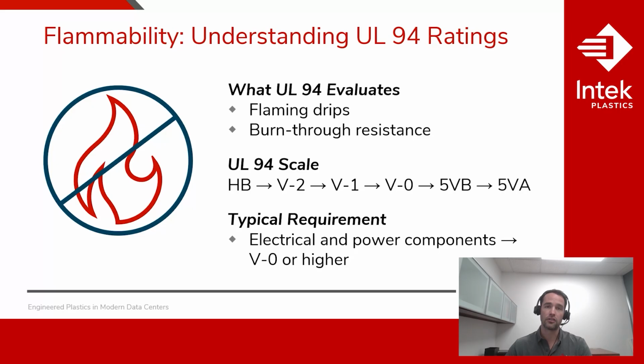For the most demanding applications, you'd be looking at the 5V tests, of which there are 2 ratings. And this utilizes a specimen oriented horizontally with a flame applied underneath. For a 5VB specimen, you might have some surface damage or slight burn through. And for a 5VA rating, the specimen would resist burn through entirely. It's important to note that the flame source for the 5V tests is roughly 5 times more energetic than for the HB and the V0 tests.